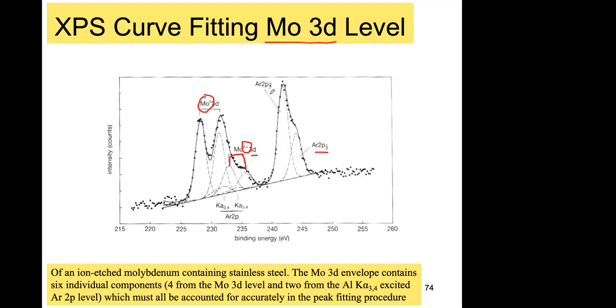So you see 2p1/2 and 2p3/2. And here, somewhere here, you see these two peaks. And this is Ka-alpha 3-4 of the argon, two peaks. So these are the same peaks, but they were excited with the Ka-alpha 3-4 photons of the X-ray source. So this is a polychromatic source. So the curve fitting gets more complicated, and you have to be careful how you analyze the spectra.